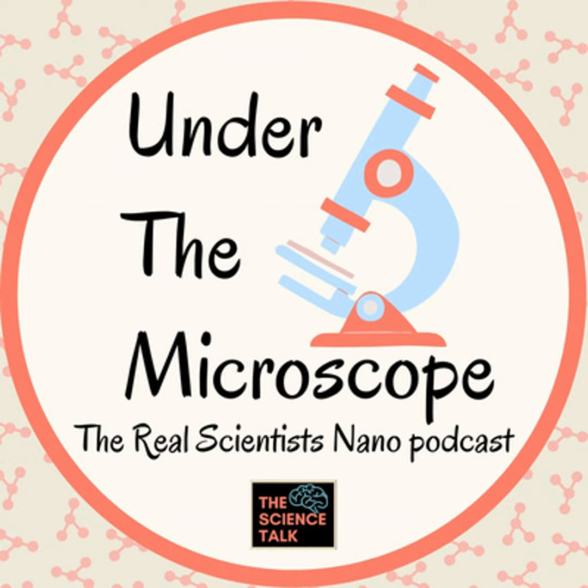It's tough. A fun one would be, and I plan to tweet these pictures, one that I mentioned earlier. So at the point where we're growing these nanowires, it was indium phosphide usually, using gold catalysts. And the normal thing that people would do in order to achieve gold catalysts, maybe three things. You could disperse gold nanoparticles. That's very easy to do, and you get this grass of nanowires. You could deposit a thin layer of gold, heat it up, and it agglomerates to nanoparticles and grow a grass. Or you could use some lithography and have this array of more ordered wires. Usually e-beam lithography gives you tiny dots, and you can use that.